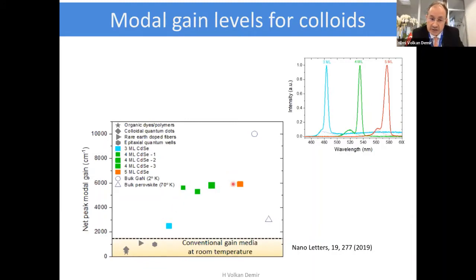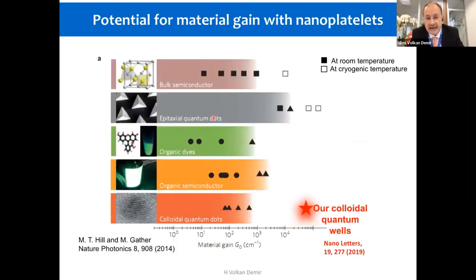These are all at room temperature, but again, to give the big picture, I should also show you bulk gallium nitride at cryogenic temperature, 2 Kelvin, really cold, and bulk perovskite. So you see this has really, really competitive results. Once again, if you would like to compare this with bulk semiconductor material, epitaxial quantum dots, organic dyes, organic semiconductors, colloidal quantum dots, now not modal gain but material gain, this is where our results fall. Therefore, we are extremely excited ourselves, and with our partners worldwide, also a variety of companies we are working with. We think finally this type of nanomaterial, extremely well engineered and high quality, will indeed challenge conventional epitaxial materials.